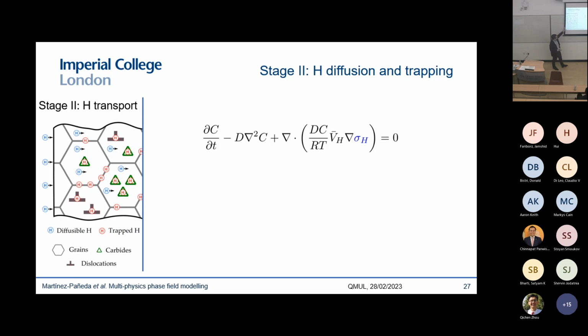And typically, hydrogen transport within the bulk metal can be described by an extended version of Fick's law. So hydrogen will be driven by gradients of concentration and also gradients of hydrostatic stress. And I like to emphasize this coupling with the mechanical part because I think that is quite important. So, in fact, if you have the steady state equation for the hydrogen transport, it looks something like this, and you can see that you have an exponential term with the hydrostatic stress inside. So it is quite important to properly characterize the hydrostatic stress.